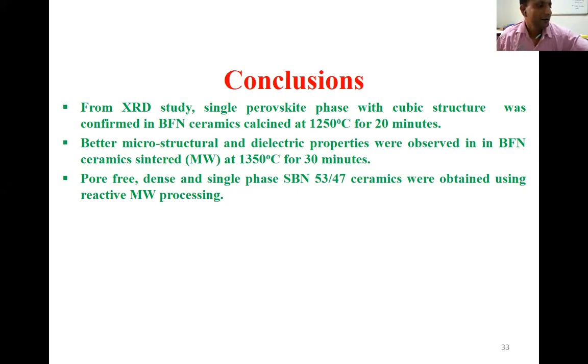Okay, so now this is just a kind of summary about the BFN system and the SBN system. The BFN system was calcined at 1250, a single phase was obtained, and we obtained better electrical properties. This BFN system was sintered at 1350 for 30 minutes. And of course, for this particular SBN composition we obtained good pyroelectric properties, as I told. Our whole purpose of selecting this particular system was for pyroelectric application.